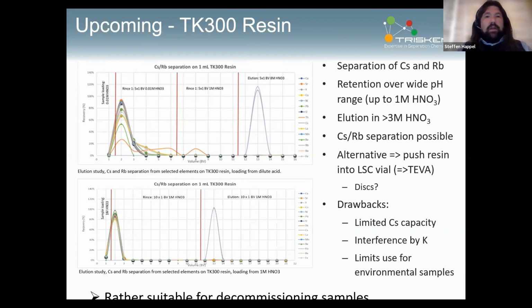So that might be a nice application, just concentrating the cesium from a water sample using a disc, then rinsing off impurities, putting the disc in the LSC counter, and counting the disc. One of the drawbacks quite clearly is that the capacity for cesium is quite limited. It is interfered with by potassium, both of which will limit its use for environmental samples.